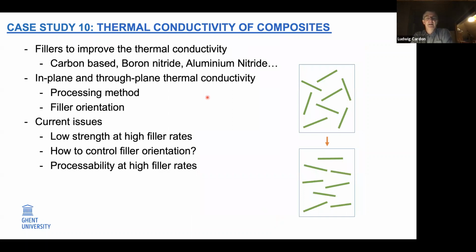Okay, yes. The last case study, very briefly, to highlight what we try to investigate in our labs, is the so-called thermal conductivity of composites. In general, we know plastic is a very bad heat conductor. Let's say 0.2 compared with steel, where we have 7, 8, or 10. So it's a factor of something like 20 difference in heat conductivity. So can we optimize this? Well, where is the problem?